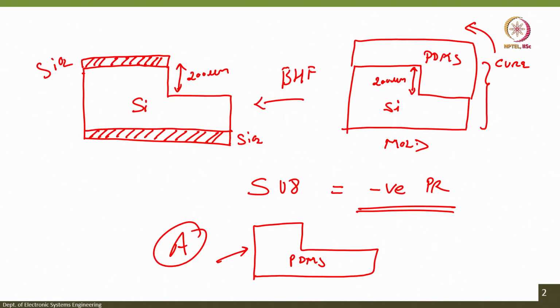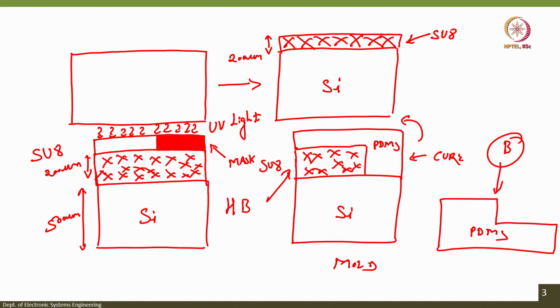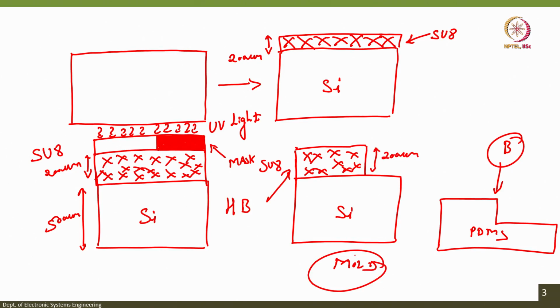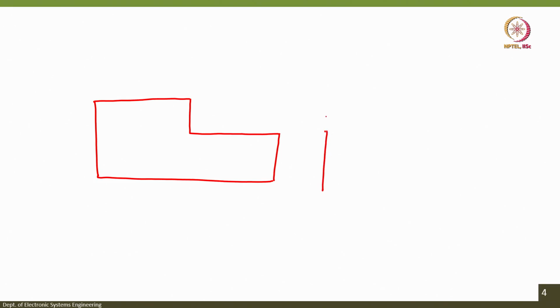Yes, but both are created differently: one using silicon etching, which we call micro machining, because we have etched 200 microns of silicon and then created a mold. In this case, we have performed photolithography and created an SU8 step, the same 200 microns. So, both ways you can create what we call a mold. All right. Now, what is the difference between the mold that is created with silicon and the mold that is created with SU8?